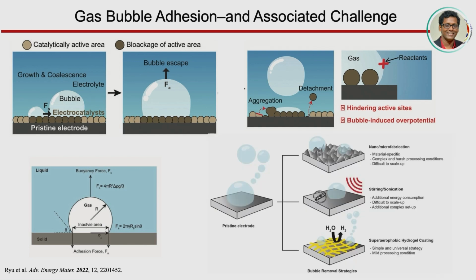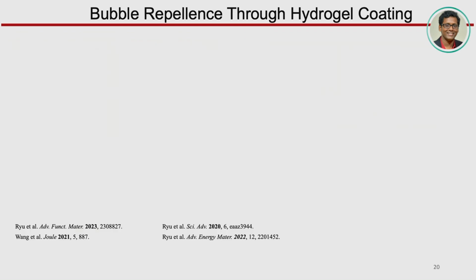So what is the remedy? Either you go for this tailored sonication so that you can get early detachment of the bubbles, or some sort of conical shape of this topography, which is not always possible with all different kinds of catalytic surfaces. Another solution is to play with bubble repellent coating, which was introduced recently based on hydrogel formation on